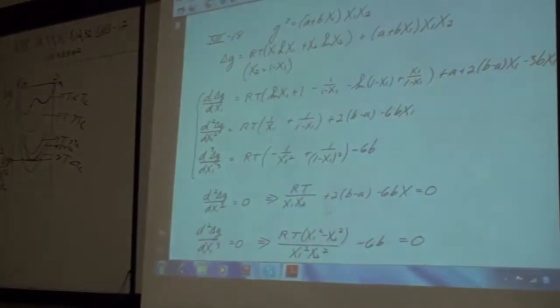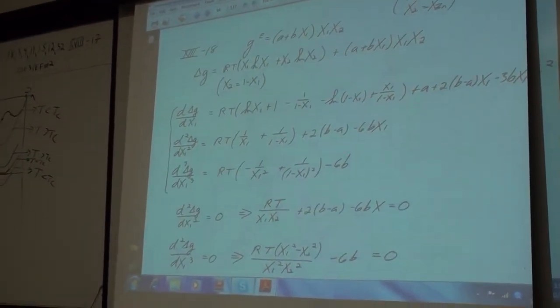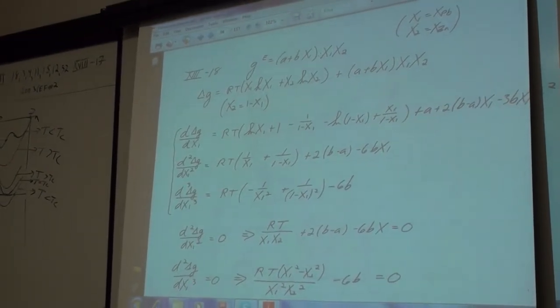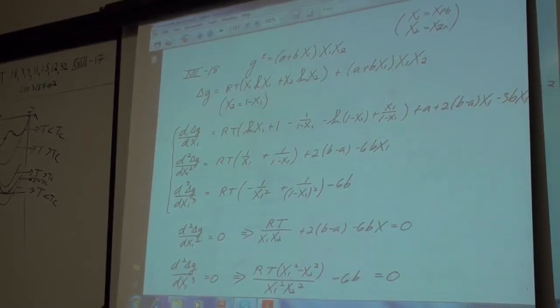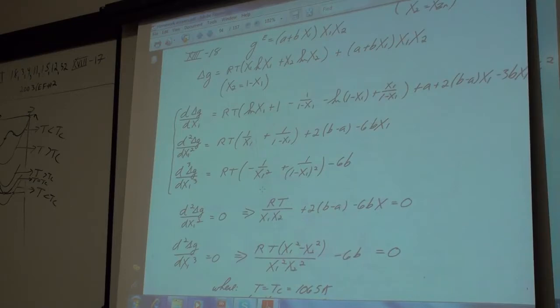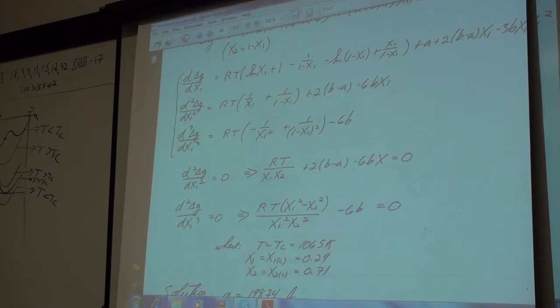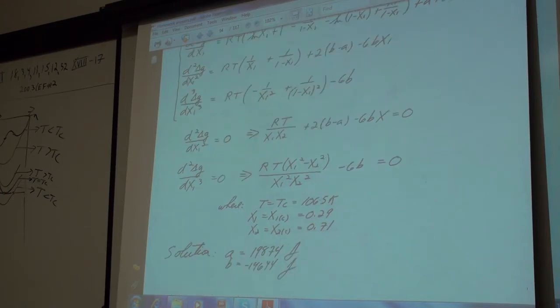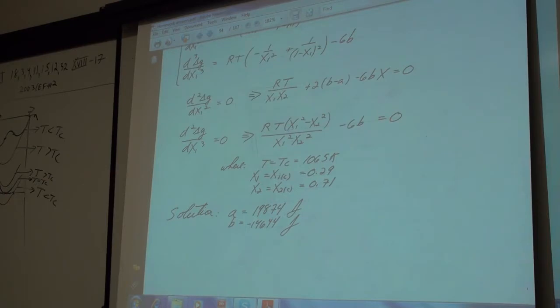Okay, so if we went to the answers, what I've run is that the excess Gibbs energy is given by the equation you were given. It's the second derivative of delta G, not the second derivative of GXS, but delta G. So the delta G of mixing is the ideal mixing term plus the excess term. We calculate the first, second, and third derivatives, remembering that dx1 equals minus dx2, and we set the second derivative to zero and the third derivative to zero. We get two linear equations in A and B, which we can solve, putting in the critical temperature and the critical composition, and we end up solving for A and B.